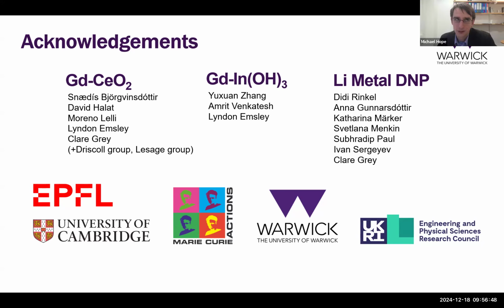As to whether you need DNP just to see it, that would depend on the concentration, and I don't know how concentrated lithium ions are in a biological system. I mean, 7Li NMR is reasonably easy as NMR goes. The pitfall is really the fact that we have a very, very narrow shift range. Every diamagnetic lithium salt is within around a ppm. And so actually getting discrimination and useful information from those diamagnetic systems is very difficult.